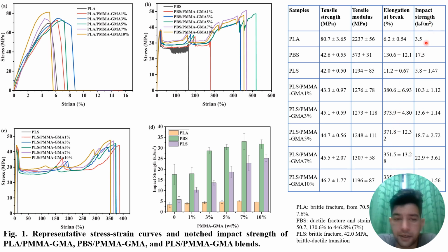After that, impact strength. PLA has very low impact strength, PBS high, and the PLA/PBS blend is also low. So after making the blend, the impact strength is 5.8, but after adding 1% compatibilizer, it increases almost double, and after that as the content of compatibilizer increases, the impact strength also increases, which shows the brittle-ductile transition.